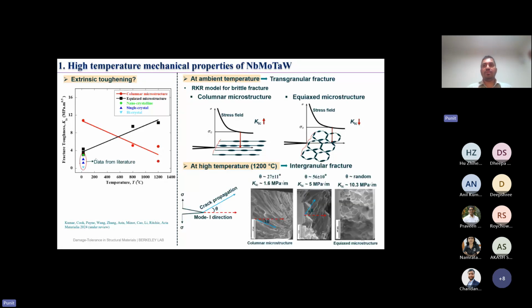But at high temperature, where you are going through this intergranular fracture, the fracture toughness of the columnar grains depends on how these columnar grains are aligned with the direction of crack propagation. And you can see as you increase the theta value, the fracture toughness or fracture resistance also increases. It is highest in the case of equiaxed microstructure, where in addition to tilting of the crack, you also have twisting of the crack, and the combination of both gives the highest fracture resistance in equiaxed microstructure at 1200 degrees C. So this is what explains the fracture resistance in niobium, molybdenum, tantalum, tungsten.